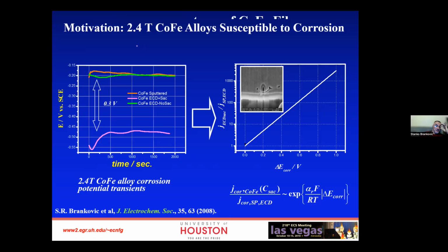In the literature that I'm going to give you to read, you will understand that the design of the additives is quite complicated, in that you need to know exactly what your film is supposed to do. If your film does not need protective properties and is focused purely on magnetic performance, less on mechanical integrity, then you just minimize, for example, softness and maximize the moment.